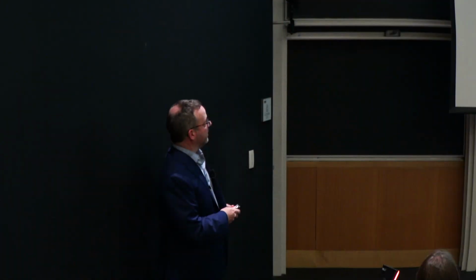So in this particular reaction, we developed a tandem catalyst system where the first catalyst converts the epoxide and CO to the lactone. We can follow this by in situ infrared spectroscopy by looking at the carbonyl, and you can see the lactone grows really quickly and declines as the carbonyl stretch for the polymer grows and levels off. At about 6 hours, if you open up your reactor, there's no epoxide or lactone, there's only crystalline polymer left behind.